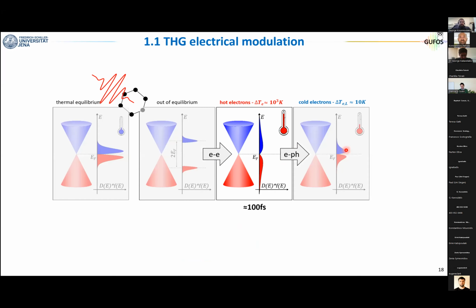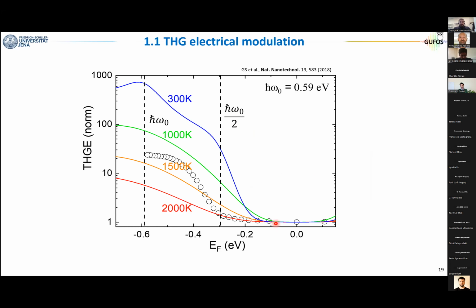Now, when we do our experiments of third harmonic, we use pulses that are very short, in the range of 100 femtoseconds. The third harmonic is generated only within the pulse duration, and this means that in our experiments, the electronic distribution is dominated by this very high temperature. And now, if we take again our experimental data, the white points, and overlap them with the theoretical curves, but this time we use higher electronic temperatures, I don't plot the 0 Kelvin, I start from room temperature, 300 Kelvin. You see that our experimental data are also very far from 300 Kelvin. This is a logarithmic scale. Instead they fit quite well with temperatures in the range of 1000 to 2000 Kelvin. And now I go back to the previous questions. Where does the linear response, the Chi1, play a role?